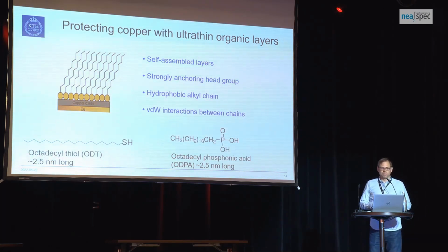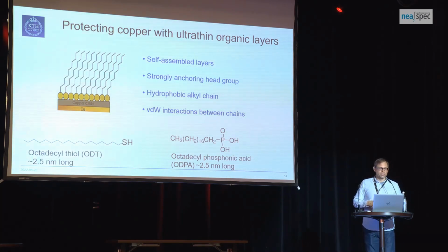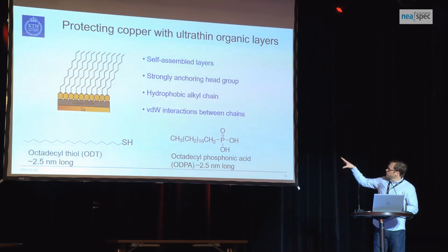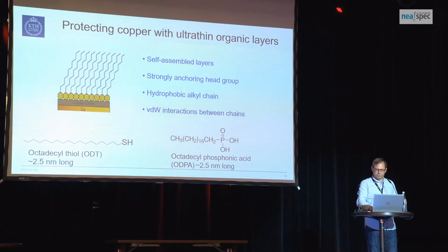And we did this in a self-assembly process. We had an ethanol solution with these molecules. We just put down our copper surfaces. We waited some time, and then the molecules assembled on the surface. And the reason we thought this could work was that these molecules are hydrophobic. They have a nice packing. We have measured with sum frequency spectroscopy. So that's why I thought this could make a good barrier.